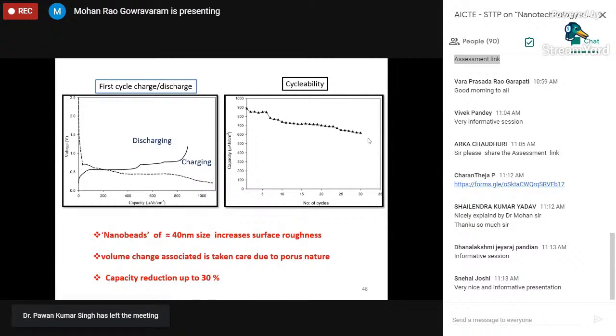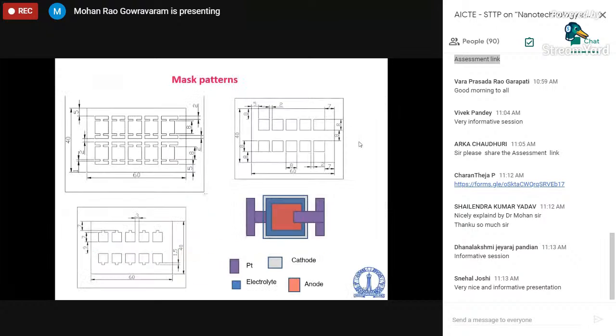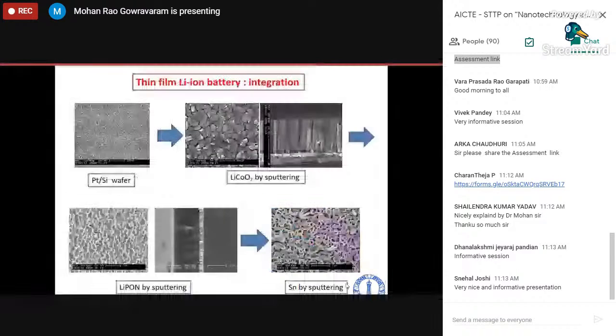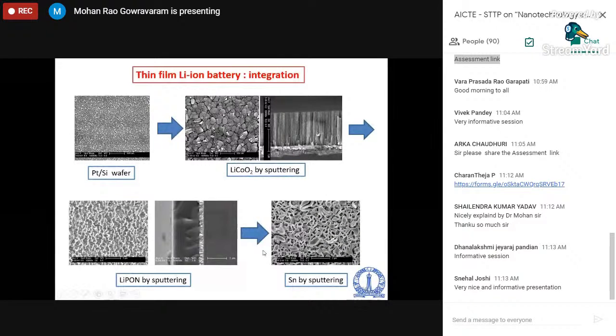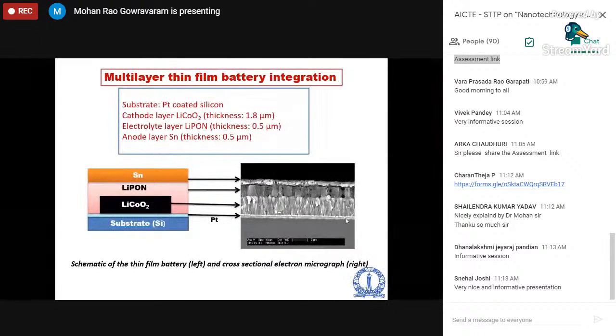Okay. So you deposit this, and for isolating each of these, you have different masks so that the battery structure is deposited. So you take a platinum-coated silicon wafer and then deposit lithium cobalt oxide by sputtering. This is the cross section. This is a very dense structure. And then deposit lipon by sputtering. So you can see the cross section here. And then tin, a porous layer, by sputtering. And now this is the cross section of your entire battery. Cathode layer of 1.8 micrometer thick, electrolyte layer of 0.5 micrometer thick, and anode layer of 0.5 micrometer thick. So now your battery is ready.